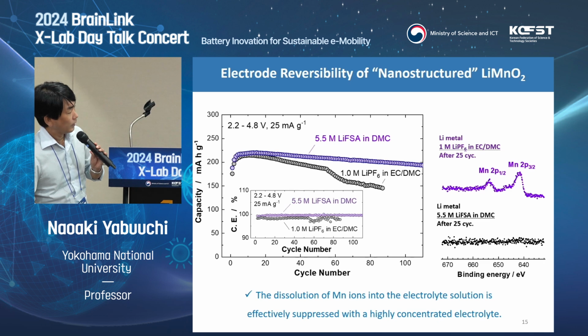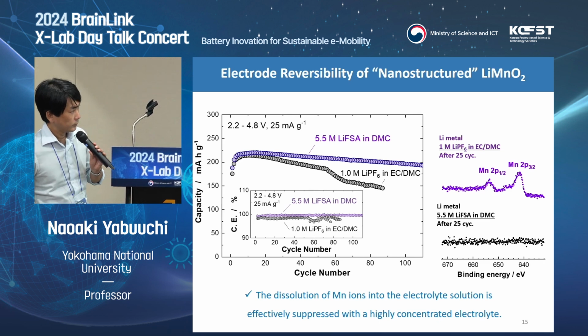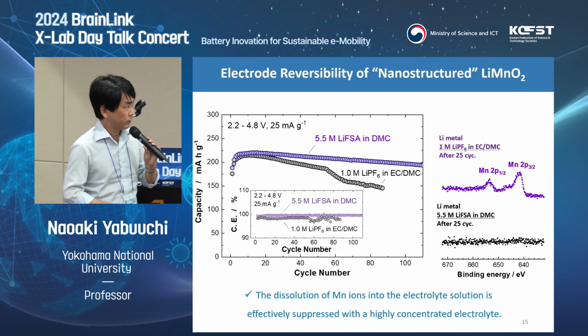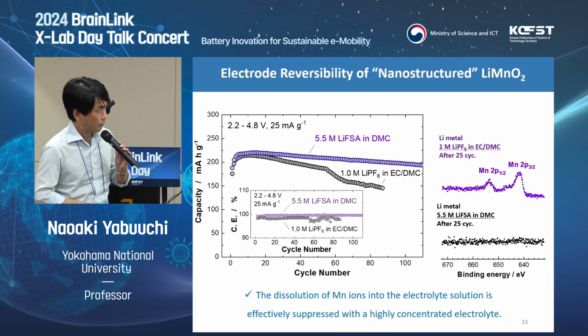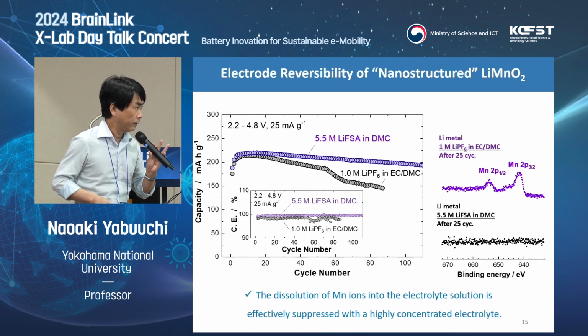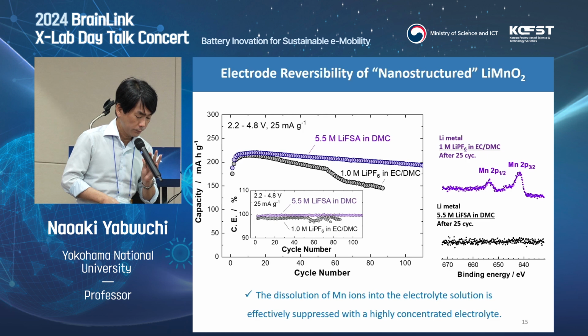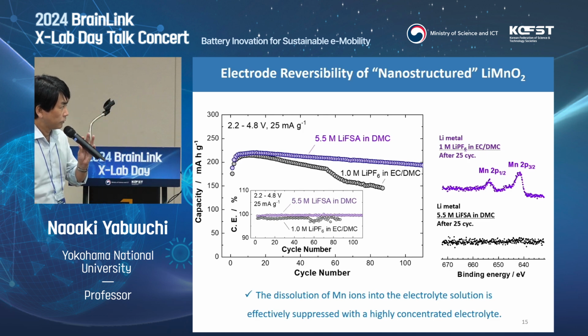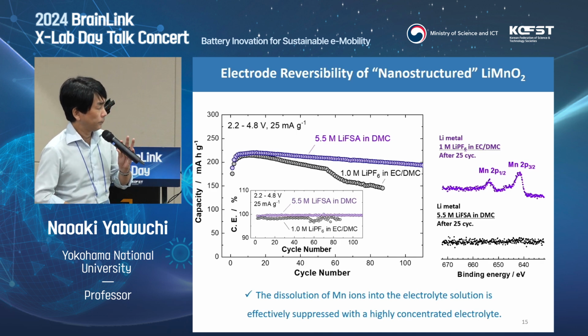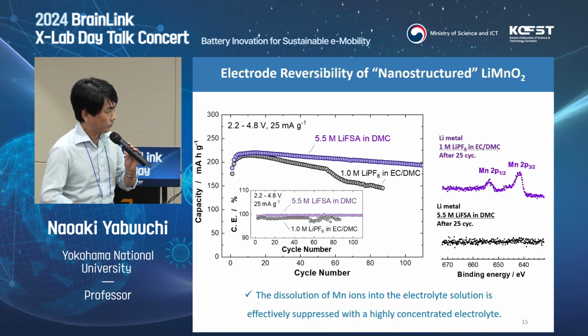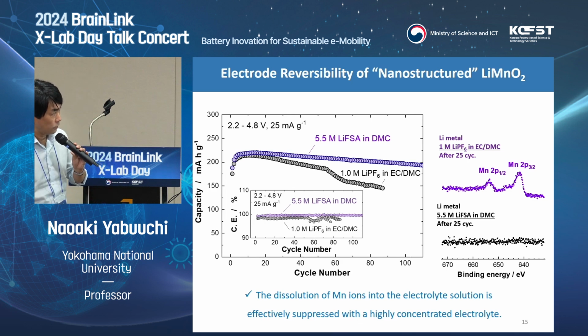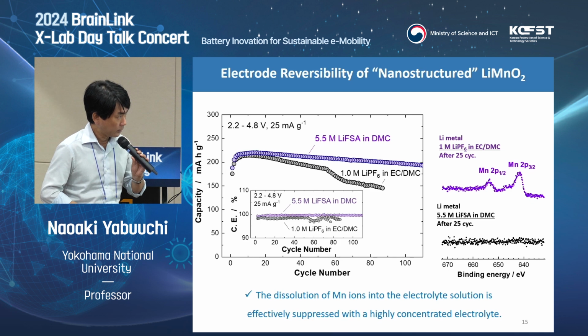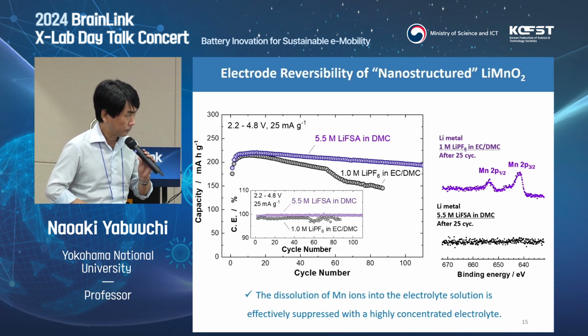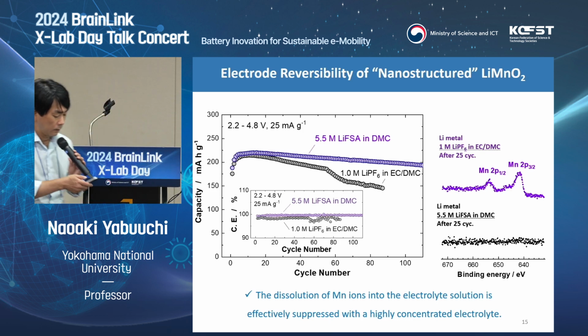Okay, again, electrolyte is important. Highly concentrated electrolyte solution clearly improves reversibility. Because of the concentrated electrolyte solution, all of the solvent is already solvated to lithium ions. We have no free solvents. Therefore, highly concentrated electrolyte solution effectively suppresses manganese dissolution. Now cyclability is clearly improved and also we get better Coulombic efficiencies. Now we can achieve 90% capacity retention even after 100 cycles with nanostructured lithium manganese O2 with a highly concentrated electrolyte solution. And also after 25 cycles, you cannot detect dissolution of manganese ions at metallic lithium surfaces.